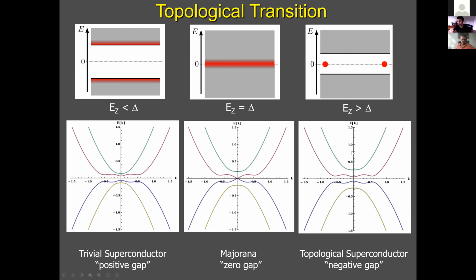So then a mysterious thing happens that it actually reopens. Well, it is not so mysterious because the reason why the gap was closing is because Zeeman energy was growing and the states were moving together, and then they just crossed through and kept going. And that's what we have on the right. However, the gaps at finite momentum minus k Fermi and plus k Fermi are still protected by spin orbit, so they change very little. So what we have as a result is that in the middle at k equals 0, the gap closed and reopened, while the other gaps stayed as they were. And so we inverted the bands. Is this helpful? Okay, yeah.